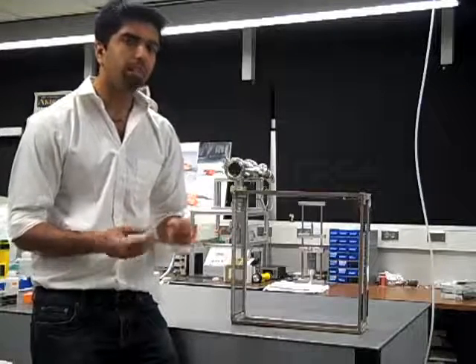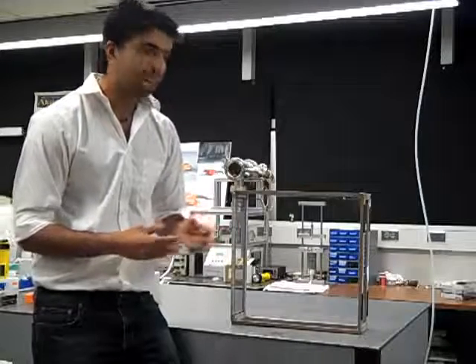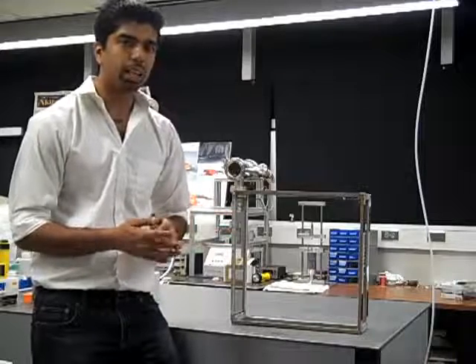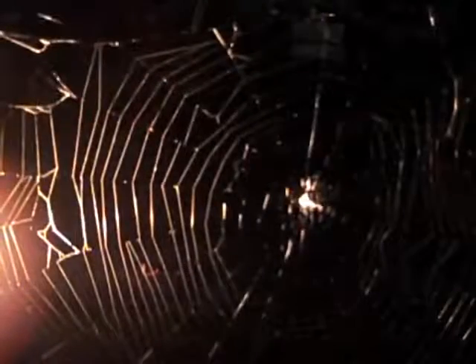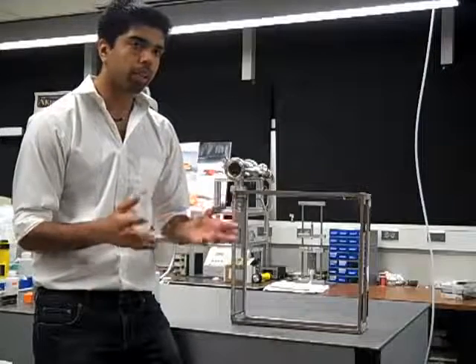What we showed in this discovery by micro-mechanical stretching of these glue droplets is that the elasticity — or should I say the viscoelasticity — of the droplets increases the adhesion by around two orders of magnitude, which is good because it helps the spider hold onto fast-flying insects when they come onto the web, because of the viscous forces.